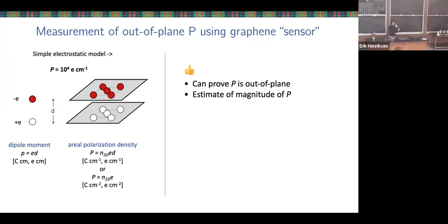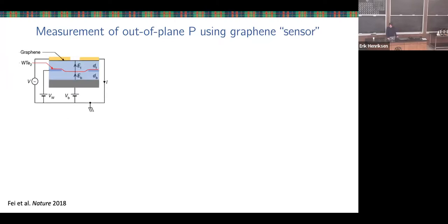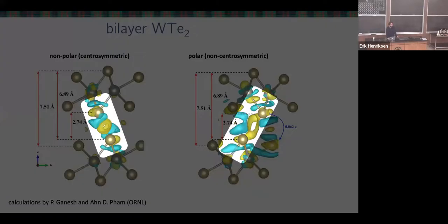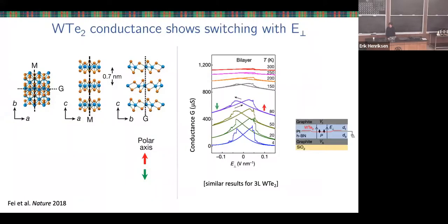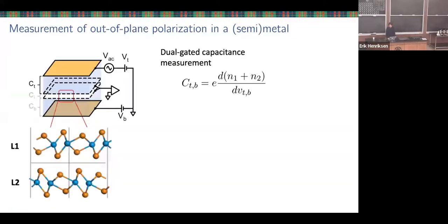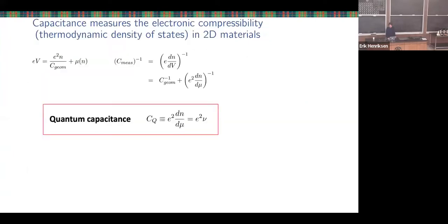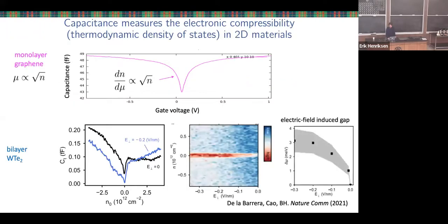The electron band comes down, the hole band comes up, and so it's not totally clear to me. We think we started with a semimetal with a very small overlap and applied an electric field and opened up a small gap. I think that's what some of our measurements indicate. These measurements seem to indicate that there's a small gap that we're opening up on the right here.